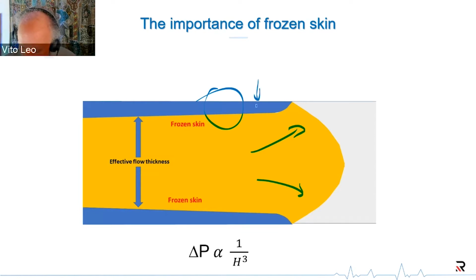But let's say that you typically end up with some sort of thickness, which I'm calling small h here. Now, what is the order of magnitude of this? It's not uncommon at all to be between 100 and 200 micrometers, so 0.1, 0.2 millimeters. It's fairly typical. Now, you can imagine that if you're molding a 3 millimeter thick part, losing 0.2 millimeters of flow channel on each side is not going to be a dramatic loss.